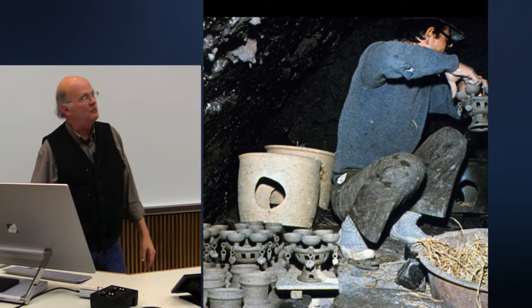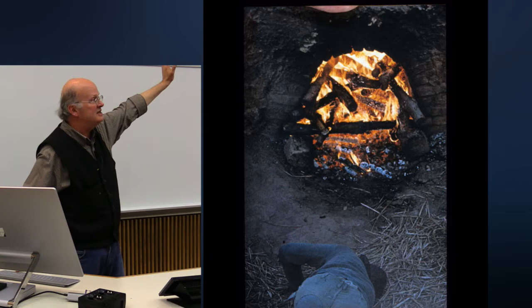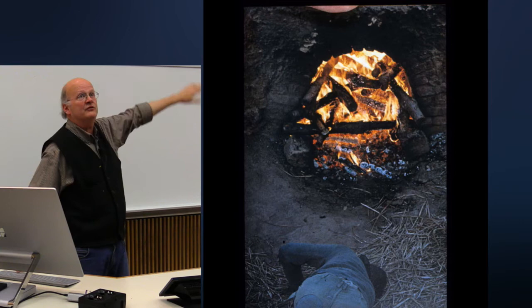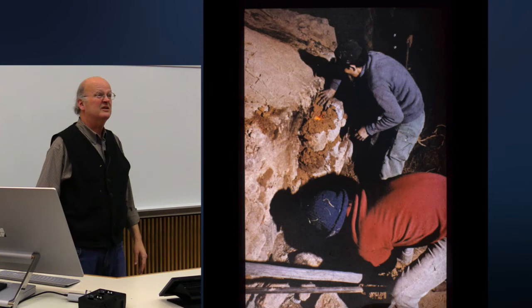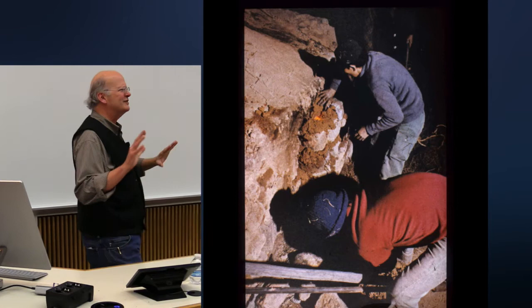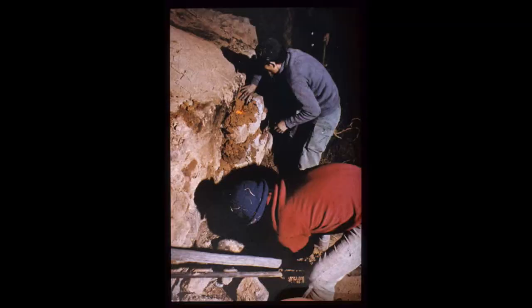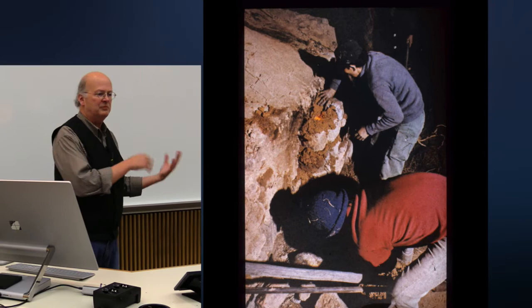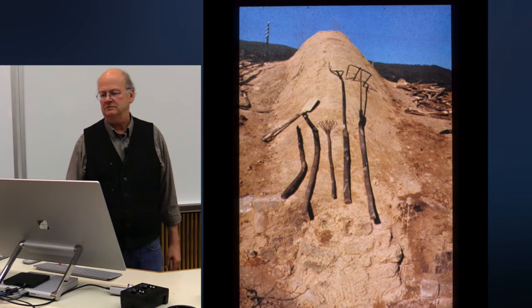This is just loading the kiln, then firing it for days until it reaches a high temperature. This is yellow heat pushing white heat. And at the very end, they stuff it full of fuel. And then they seal the whole kiln. We usually call it clamming the kiln, right? I don't know why. But anywhere there is a wisp of smoke coming out, another handful of mud goes onto the surface, trapping all that excess fuel in there. And that is responsible for changing the color of the clay from red to black. That's the cooling kiln, and that's the pots that came out of it.